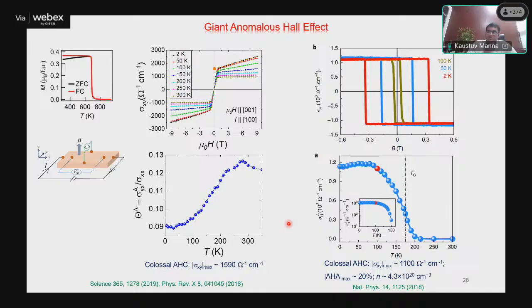Otherwise, even though there is Berry curvature far away from the Fermi energy, it will not affect the anomalous Hall effect. In these two compounds, it so happened that the Weyl points are very close to the Fermi energy. As a consequence, you get a large anomalous Hall. But cobalt 2 manganese gallium, this work is so important because it's a room temperature ferromagnet. Its transition temperature is around 700 Kelvin.